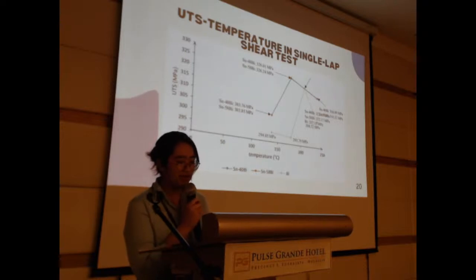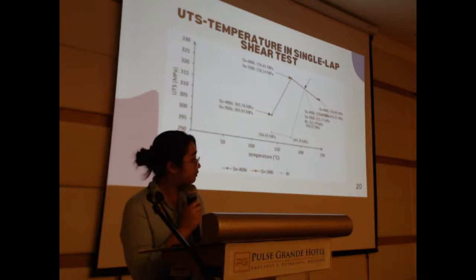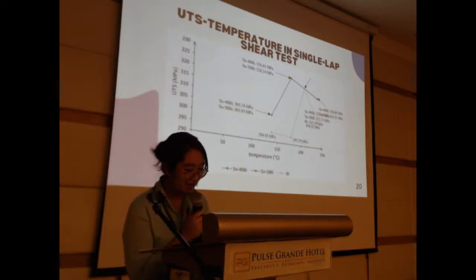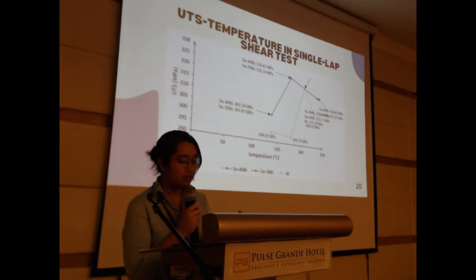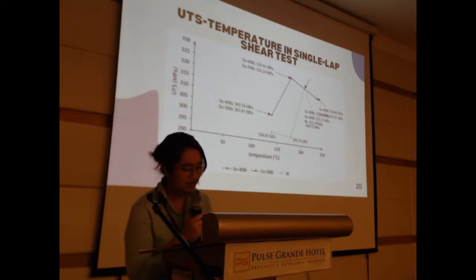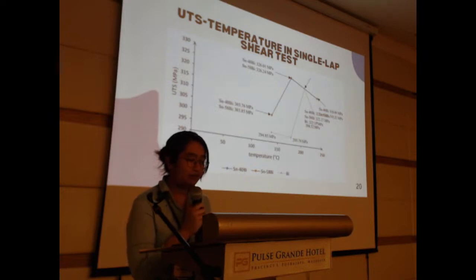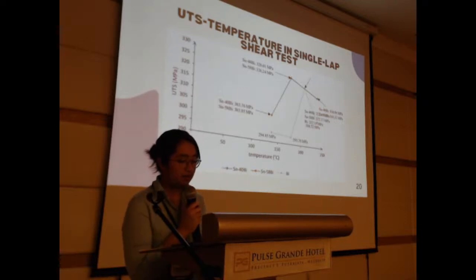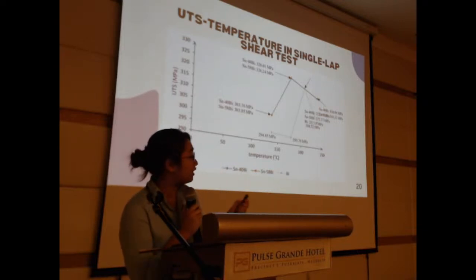But increasing in IMC layer does. High IMC layer, then it tends to get brittle. So from there, we can conclude that high temperature leads to low tensile strength of SnBi.